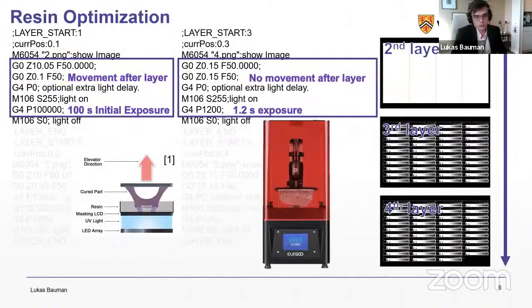So one of the issues with this printing, though, is that when you're synthesizing a lot of these materials, like the Pluronic diacrylate that we use as a crosslinker, you don't have a lot of material, so you can't use typical exposure tests. And this is an issue because these will take 10 minutes to an hour and use quite a bit of resin.